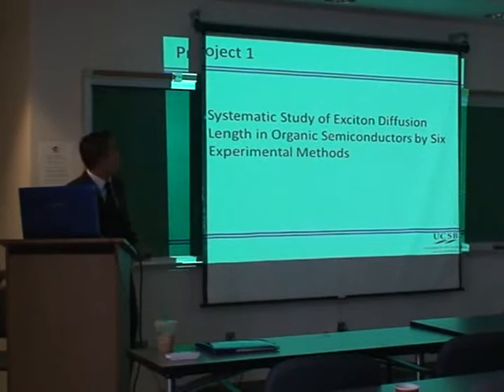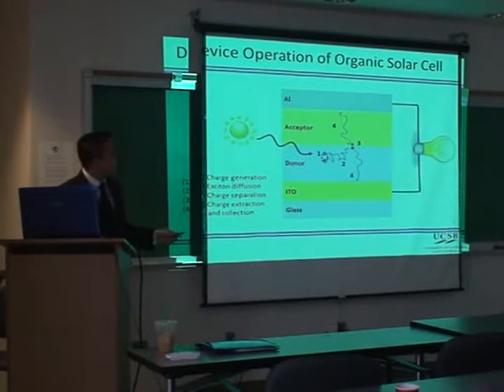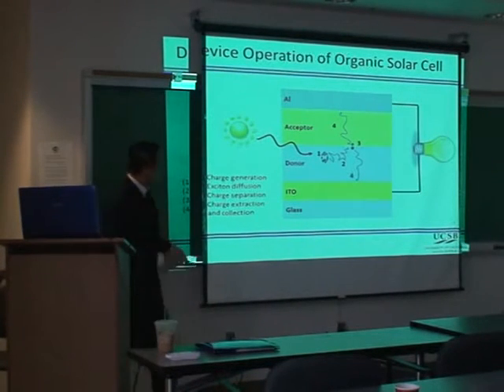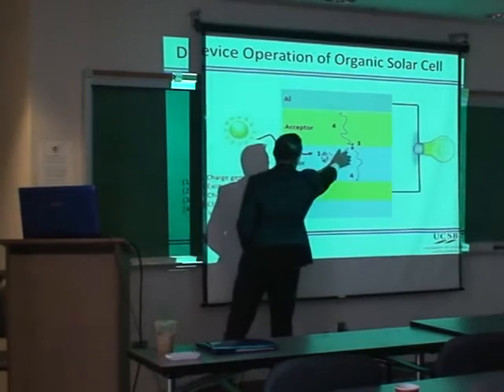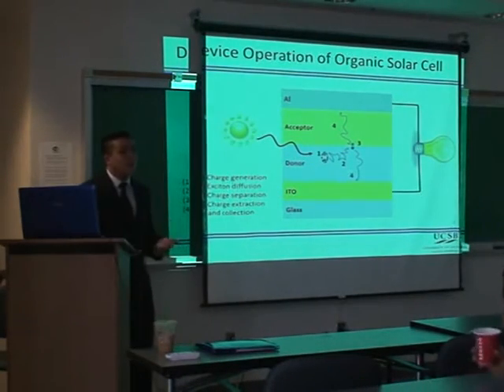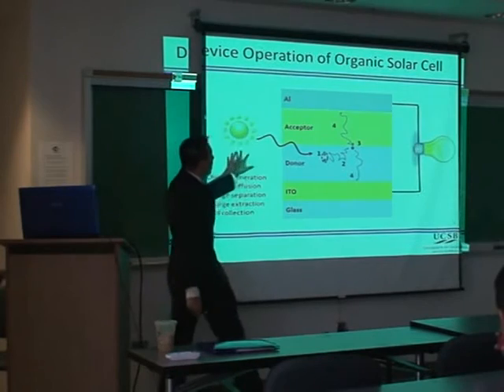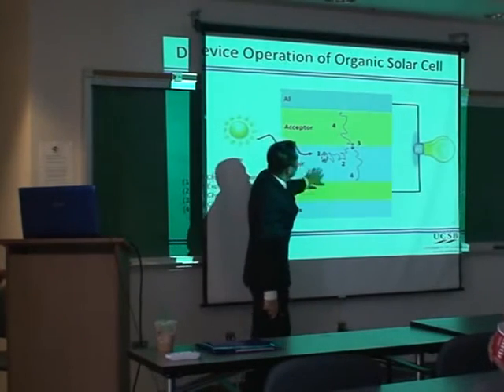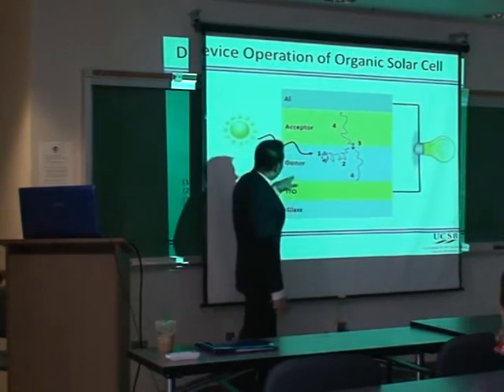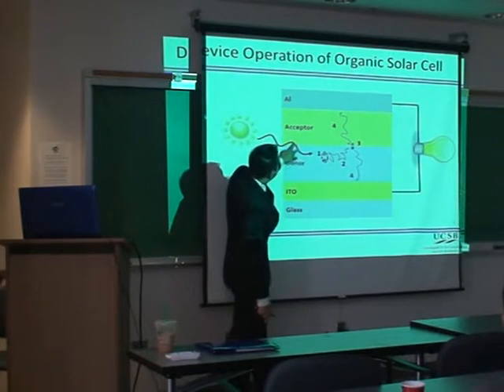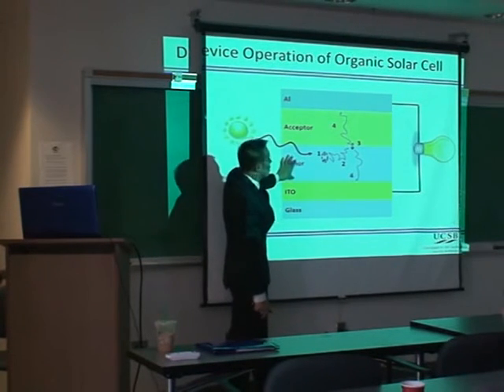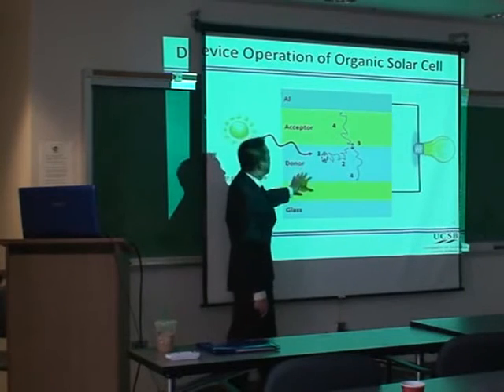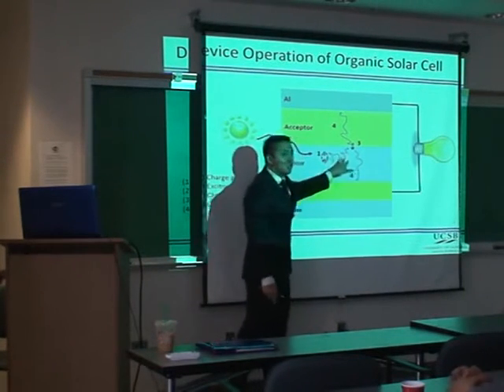So project 1, systematic study of exciton diffusion length in organic semiconductors by 6 experimental methods. So again, just want to say that I'm focusing on the step where we have just exciton diffusing. And we want to basically increase that length, because you can imagine that when light is being shined on this film, there's excitons being generated everywhere. But if the exciton is generated down here, it has not too much of a probability of reaching this interface if the diffusion length is very short.